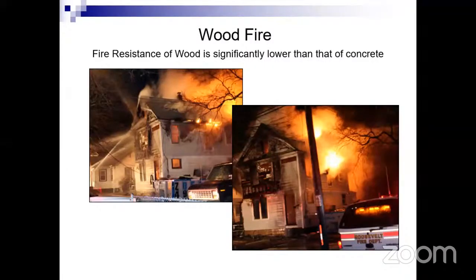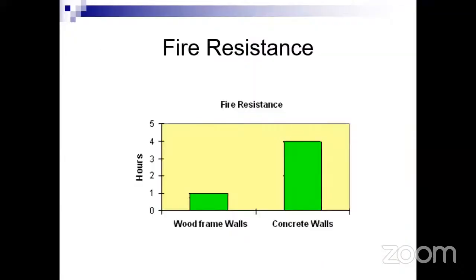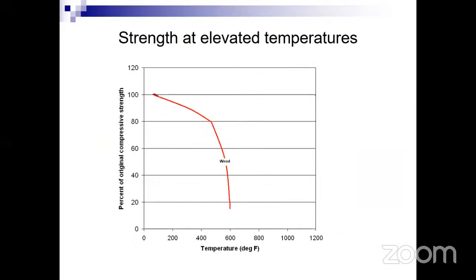We can see that there are many countries where old structures were made of wood. The fire resistance of wood is very, very low compared to concrete. We can see in this graph as well that any concrete wall will bear fire for at least 4 to 5 hours, but in comparison, wooden frame walls can only stand 1 hour of fire. Also, if we talk about the performance of the wooden structure at elevated temperature, the strength of the wooden structure falls very sharply, which we can see here.